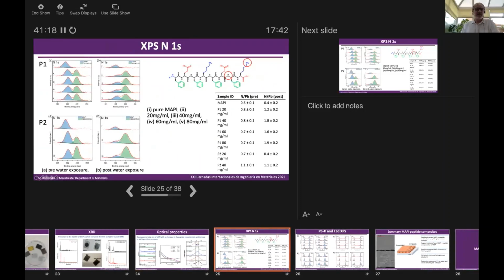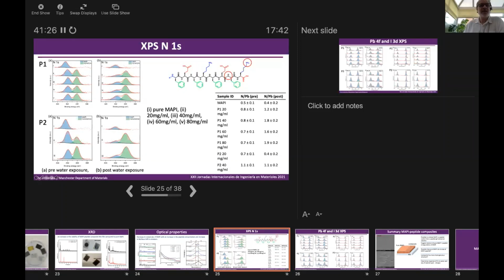So we want to look at the XPS to see whether the surfaces are indeed protected. Here, P1 at the top is the original peptide, and the one at the bottom is the one with the additional lysine. So this is the more hydrophilic peptide. For the nitrogen 1s, we have the pure MAPI here, and this is with the peptide mix. Obviously we have an additional nitrogen peak here, and that's because we've got the amine in the peptide, also giving rise to a signal.